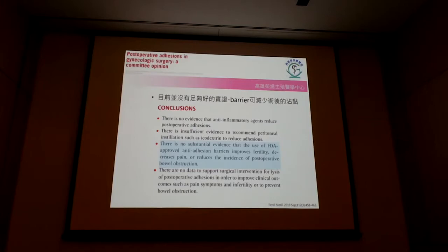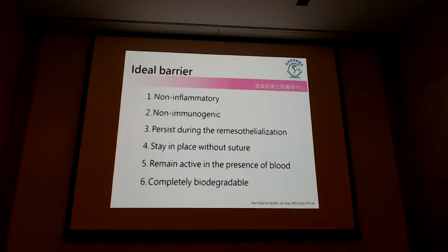I think that any ideal barrier should have the following six conditions: non-inflammatory, non-immunogenic, persist during the re-mesothelialization, stay in place without suture, remain active in the presence of blood, and completely biodegradable.